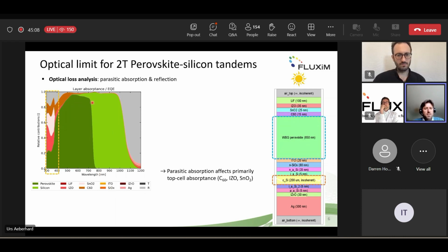So we compute the absorptance in the different parts of the device. And we see directly that parasitic absorption in non-active layers affects primarily the top cell absorptance and not the bottom cell. So it's not really useful to do a lot of work at this point to increase the current in the bottom.